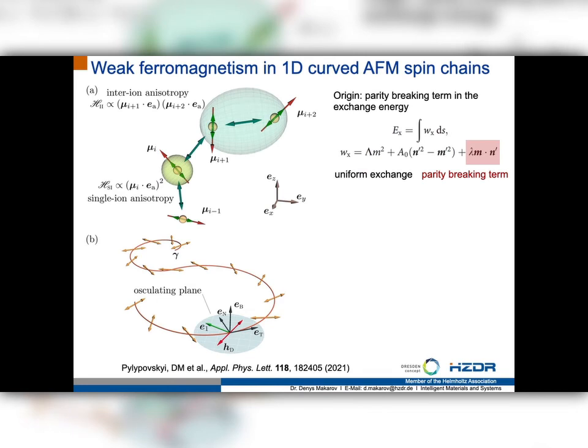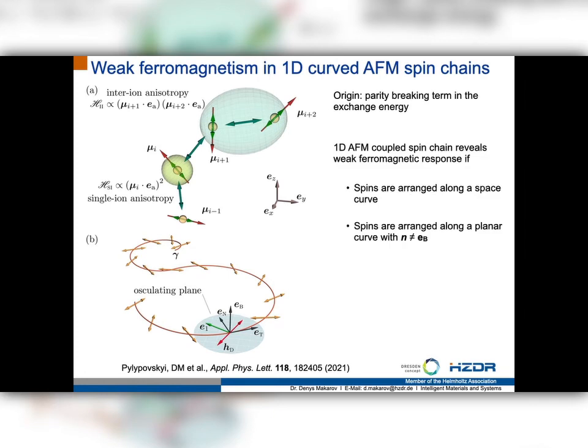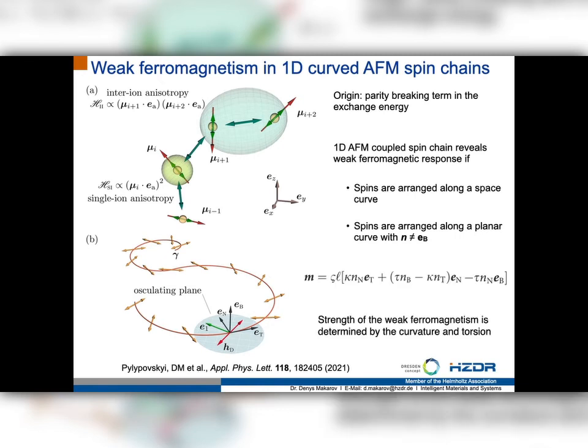Now, if we consider this parity breaking term in the energy functional, you will see that it enters also the anisotropy, and you can extend it theoretically into the understanding that a system where the spins are oriented along a space curve, so a three-dimensional curve where you will have torsion and curvature, can support weak ferromagnetism, where, for example, the magnetization will be determined by, of course, curvature and torsion in the system, and it can be sufficiently strong.